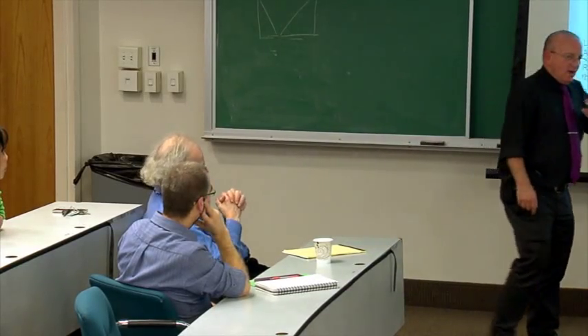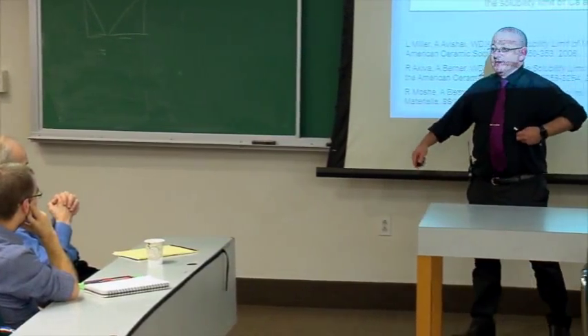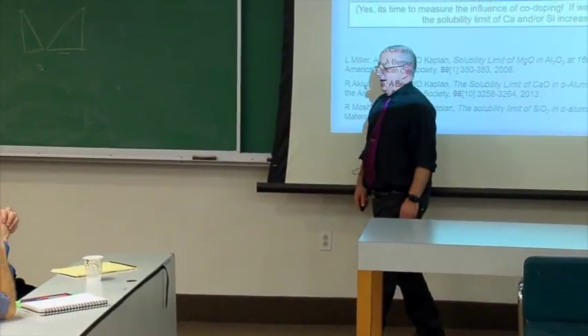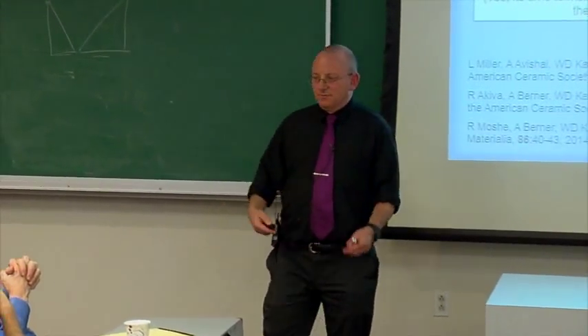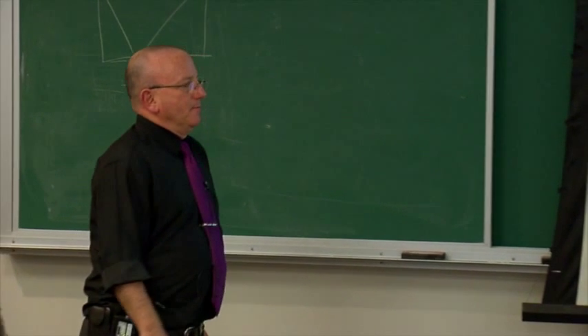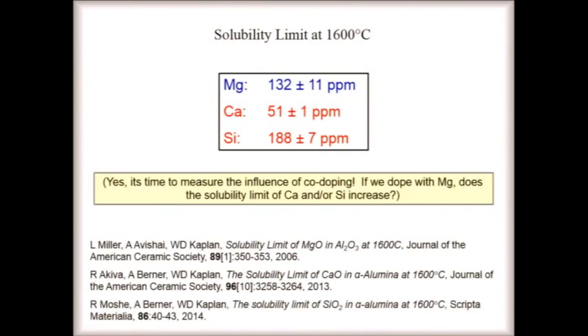Yeah, well, it's hot. It's even hotter than this. Literally, your clothes will light up. But it's worth doing it, and we've now done it for magnesium, which is what we started with, and that was 132 ppm. That's not 300 ppm that Kobel talked about. Calcium I gave to you, and the last data point which we measured was silicon, which is 188 ppm.